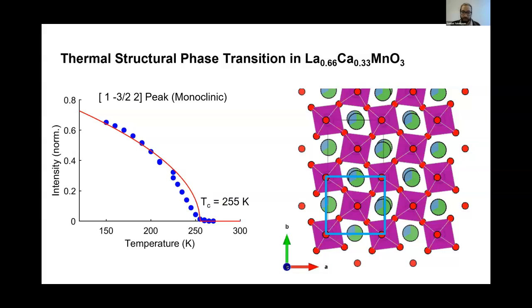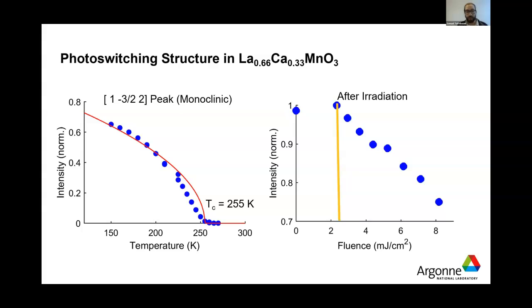So this blue box shows you the unit cell of LCMO at room temperature. And if you cool it through 255 K, you'll see a doubling of the unit cell, and this new peak, this monoclinic peak, appears with decreasing temperature. And then if you photoexcite the system, this monoclinic peak starts to disappear. And so you can think of the metallic phase as essentially a partial recovery of the high symmetry state.